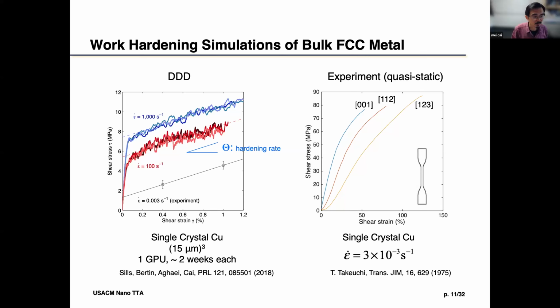So that begs the question, so we should have a one-to-one comparison, okay? Now the reason that we have to go to high strain rate is kind of a fundamental computational limit. When you go to microscopic scale, you typically also have to deal with much shorter time scales, and then you have to deform things at a very short time scale, so your strain rate is high, right? So in fact, this is not that bad compared with MD. If you do MD, then the strain rate is like 10 to the 7. So this is only 10 to the 3rd or 10 to the 2. But anyway, it would still be good to have a one-to-one comparison with experiments.